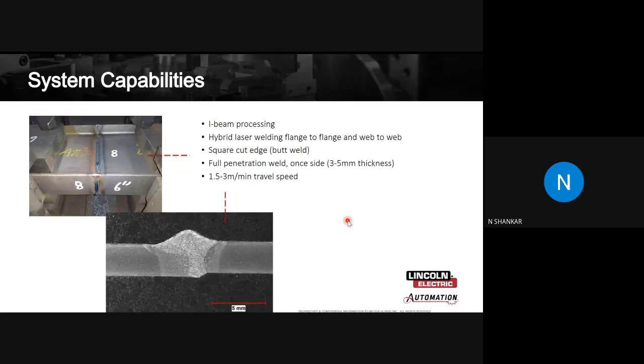Butt welds are possible, and you can travel from 1.5 to 3 meters per minute speed with full penetration from one side. There's something called OSW. You can do one side weld with 100% penetration with hybrid laser welding. So that is hybrid laser welding for you.